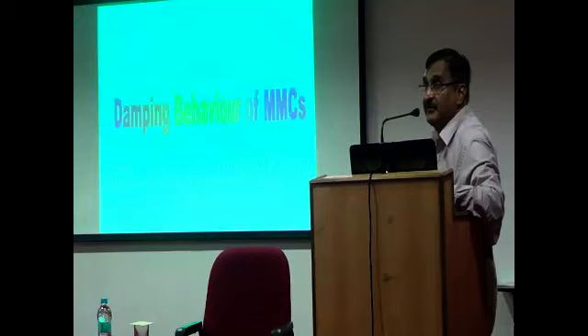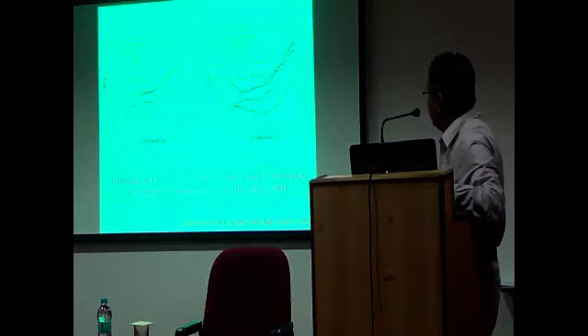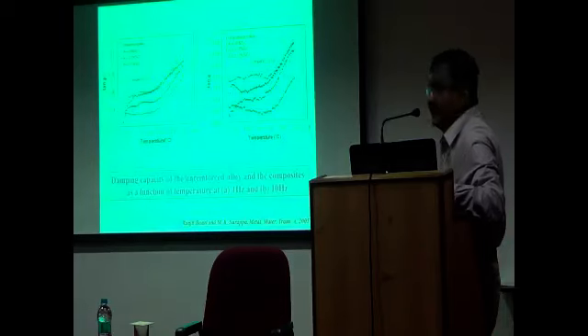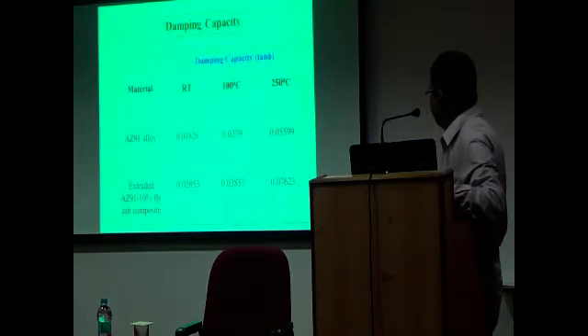This is again the damping behavior. You can see how the damping properties change. This is the magnesium damping as a function of temperature, and if you add the fly ash, you can significantly change the damping properties. You can see nearly about 20 to 30% improvement in the damping.